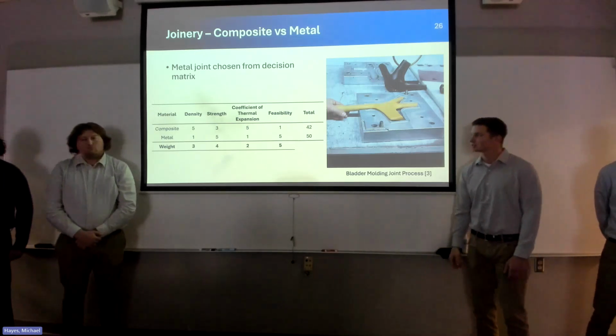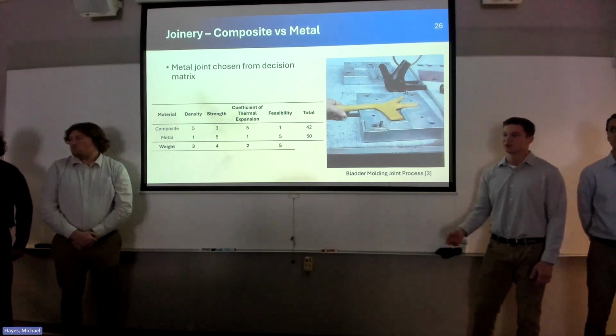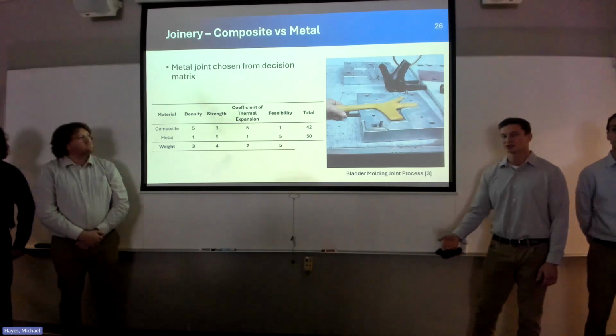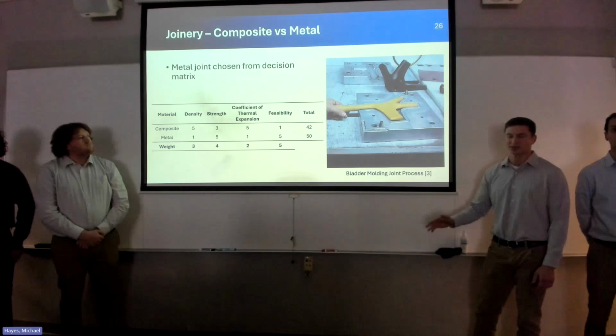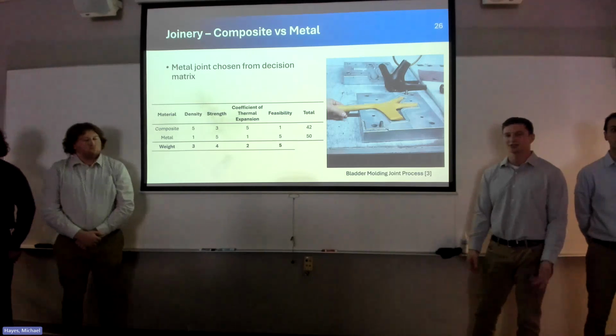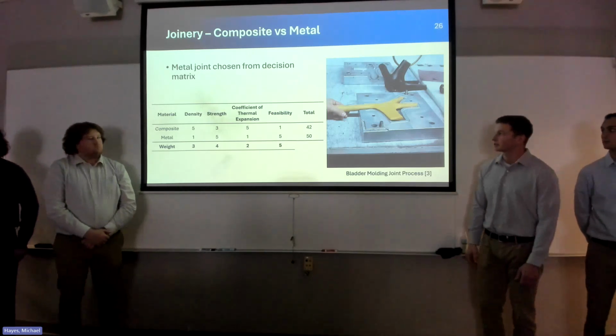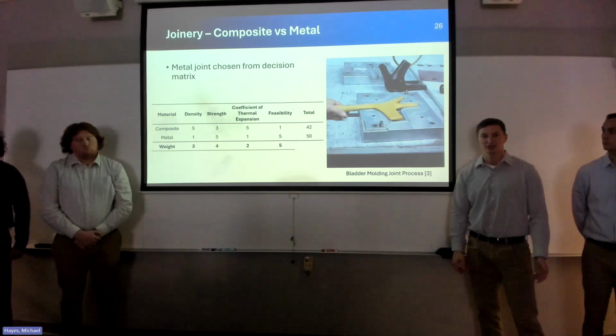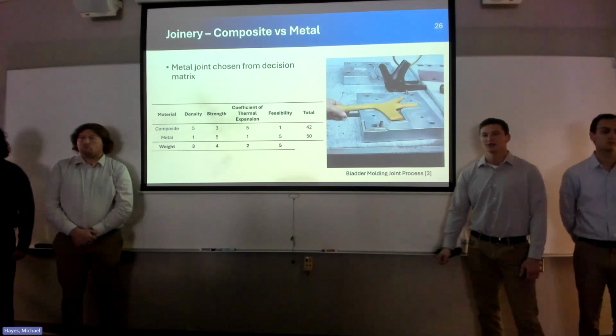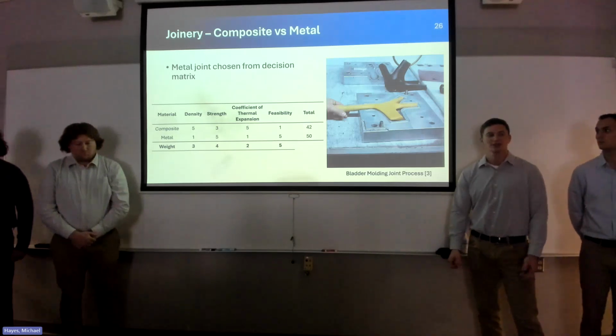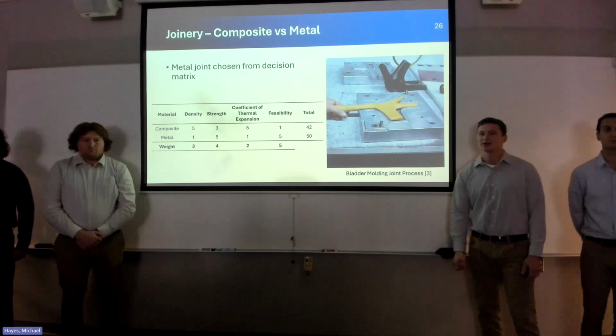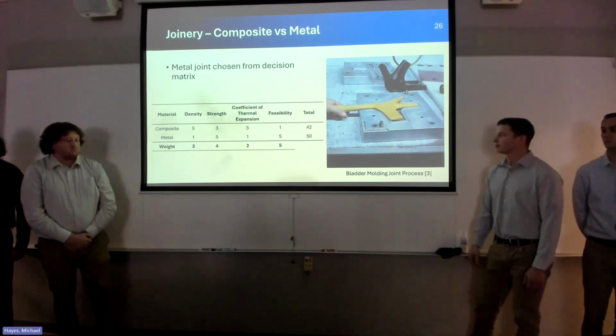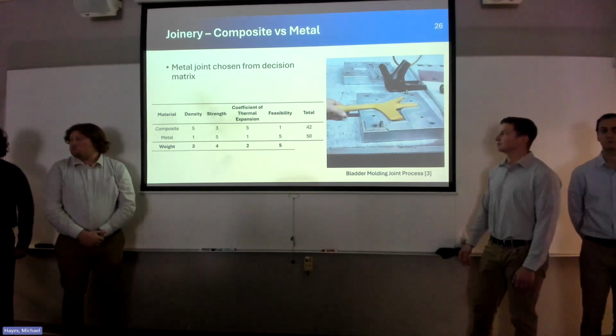The nice thing about this is that you would have the low density, which would be very nice to match that of the truss structure, as well as the strength to weight ratio, as Bryce had mentioned, is very nice for composites. Looking at the coefficient of thermal expansion, this is also very nice due to the fact that you would actually match that of the composite tube. So when there's heat added, you don't have any residual stresses in there. The only downside of this method is the feasibility of it.